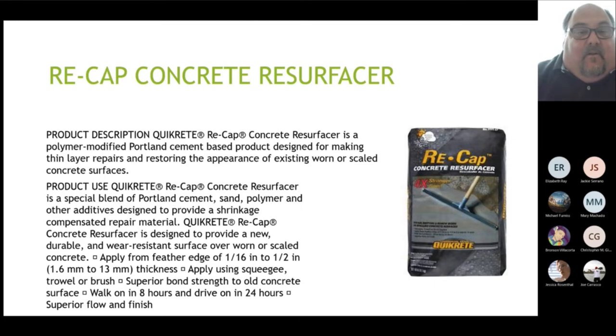If there's any serious spalling, you can actually mix this stuff up and use it as a patching repair product. Mix it up into a plastic consistency. Same rules apply. Make sure there's no loose debris. Make sure it's clean. Make sure it's damp when you put this down. Then wait 24 hours, and you can come back over the top of it.